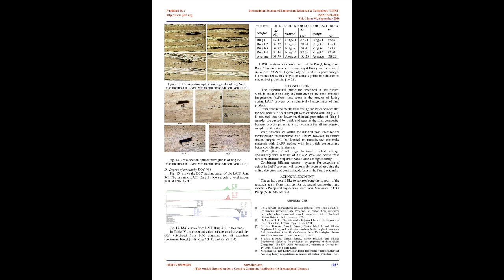D. DSC. A commonly used method for measuring crystallinity in polymeric materials called differential scanning calorimeter, DSC, is used in this study to validate model predictions with experimental results. The degree of crystallinity of CF-PEEK laminates was measured by a differential scanning calorimetry technique according to ISO 11357-3. DSC tests were conducted by means of calibrated DSC instrument equipment from Mettler-Toledo. The weights of samples extracted from each laminate were in the range of 7 to 15 mg. Dynamic tests were performed with a heating rate of 10°C/min from room temperature up to 400°C. A cooling rate of 10°C/min was then performed. For the calculation of the degree of crystallinity Xc, the expression 2 was used.